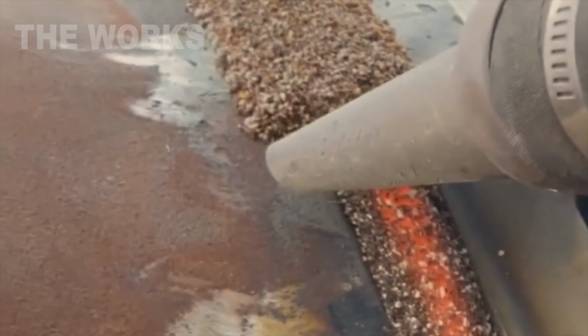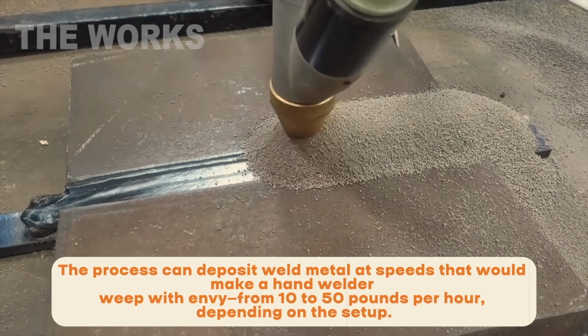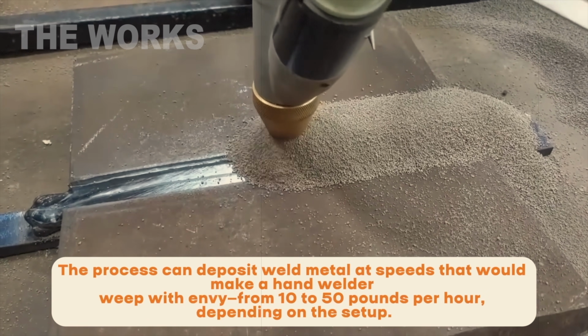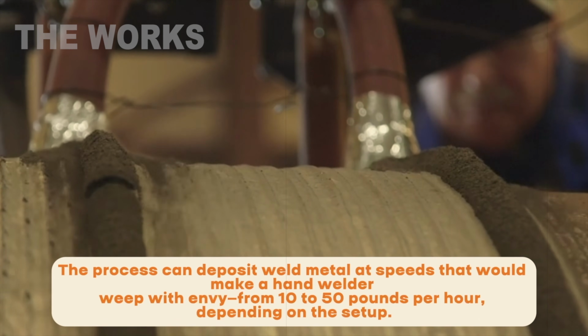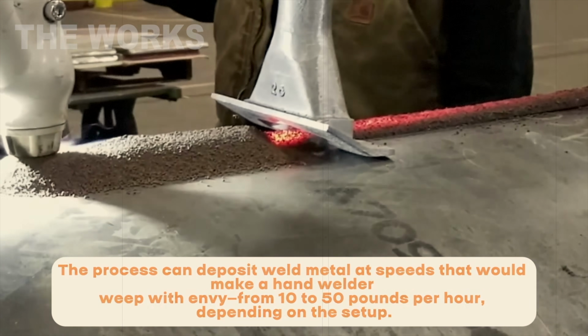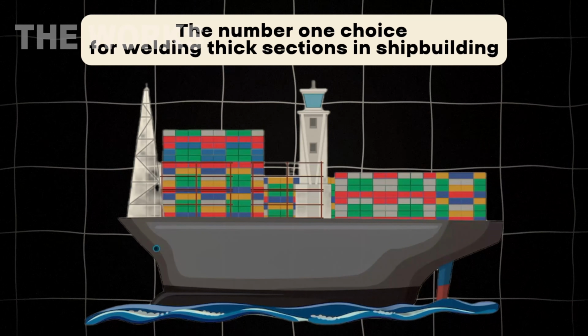That's why submerged arc welding is the #1 choice for welding thick sections in shipbuilding, pressure vessel fabrication, and structural steelwork. The beauty of this process lies in its depth of penetration. Submerged arc welding can achieve full penetration welds on steel up to 3/4 of an inch thick in a single pass.